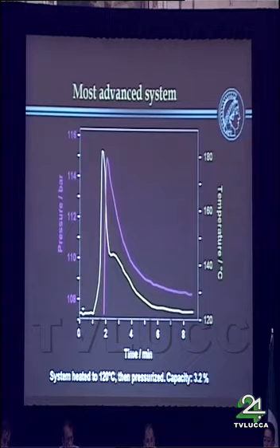And at that temperature, it's difficult to rehydrogenate the second stage, so the system has to cool down again. And while it cools down, it absorbs the hydrogen, and you see that it's basically over after 5 minutes, and the majority of the hydrogen has been absorbed, I would say, after 2 minutes. If the temperature were stabilized, we are pretty sure there would be a rehydrogenation rate on the order of 2 to 3 minutes. For, in this case, the 3.2 is plotted. We have now 3.5. There is more catalyst in there, so the expectation value is about 4.5. So we rehydrogenate about 75% of the theoretical capacity in this case.